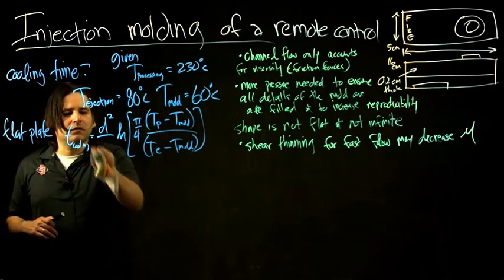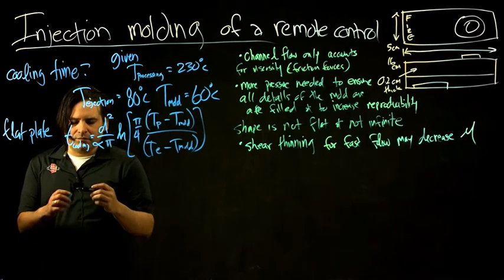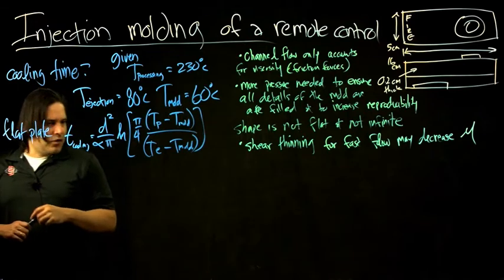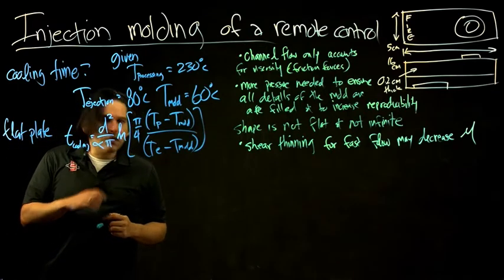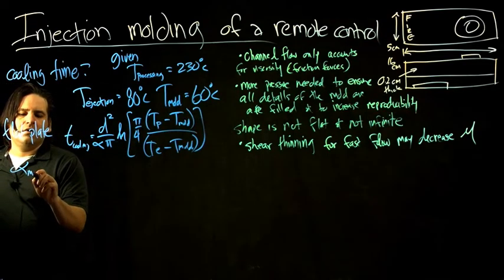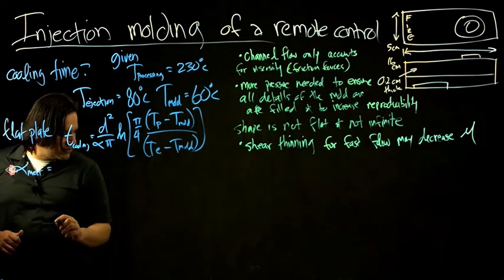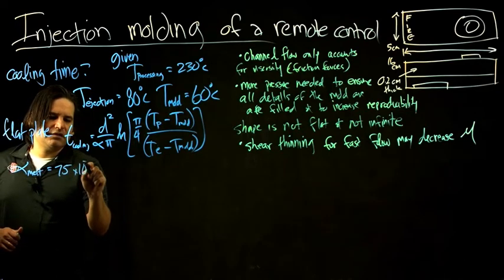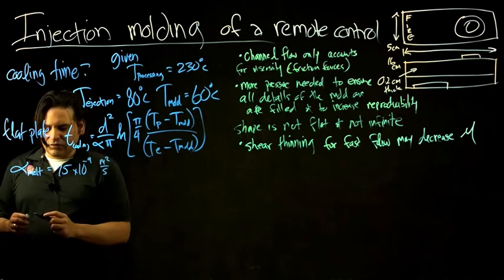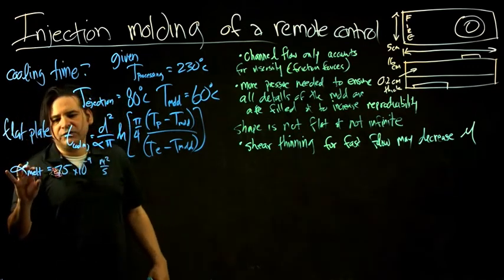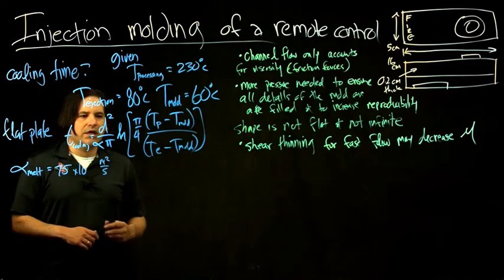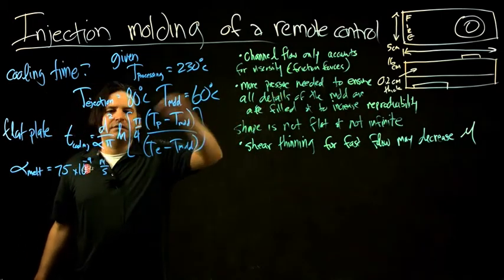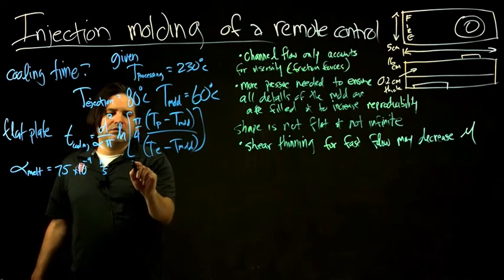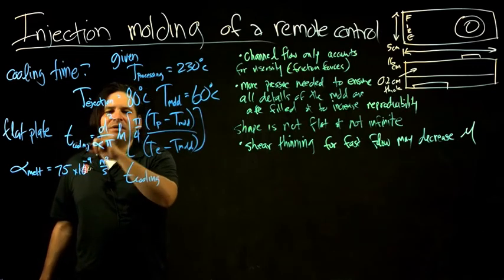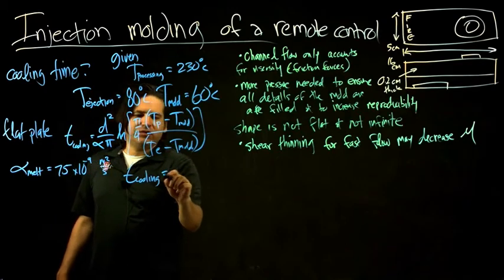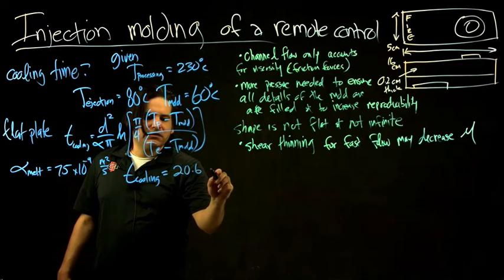There should be the thermal conductivity of the material over pi, and also given the thermal diffusivity of the melt material. Let's say that it's a constant value of 75 times 10 to the negative 9 meters squared per second, which is a nice unit to work in. And instead of thermal conductivity, it's thermal diffusivity, which is this meter squared per second. Plugging all those in, we know the thickness of this plate, we know the temperatures are given, so we can use this simplified estimate based on a flat plate. With solving this heat transfer, you get 20.6 seconds to cool.